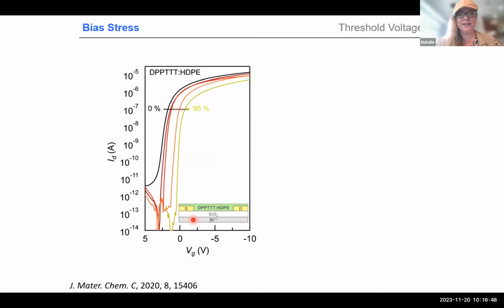So here again, you see a 3-terminal device, common gate on the bottom, insulator, source drain, and then the semiconductor. And we looked at various blends from the neat DPP-TT, with blends adding up to 95% of polyethylene. And this was measured now in nitrogen. So therefore you see even the neat materials behaving pretty well.